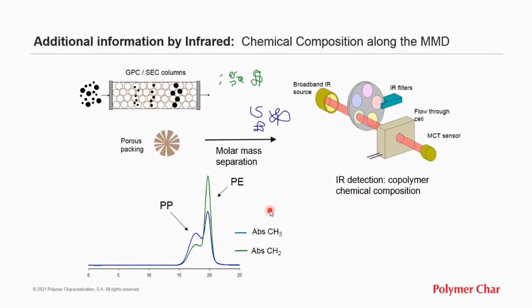So the IR detector is used with advantage as concentration detector in GPC, but most important in the case of high temperature GPC for polyolefins is that the multiple band IR detector is also used as a chemical composition detector. In addition to the total polymer concentration, the IR measures simultaneously the absorbance chromatograms for methyl and methylene groups, as we have seen. The ratio of those two signals can be calibrated to methyl group frequency, methyls per 1,000 carbons, and used to calculate the short chain branching and the comonomer fraction at every slice.